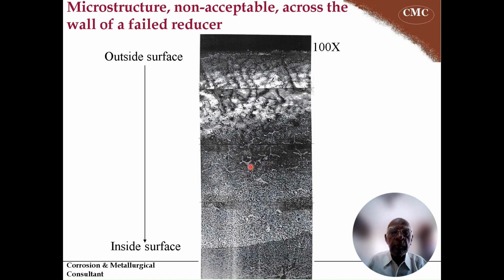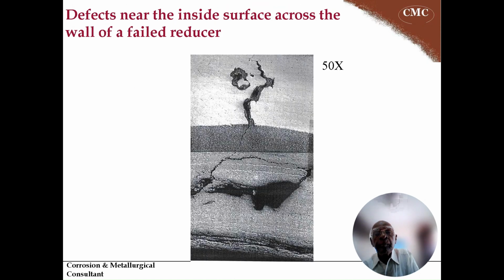The wall is only about 3 or 4 mm thickness, and due to the gradation in the microstructure, cracks develop. You can see the crack initiating on the inside, where hot gas is coming in, and then the cracks develop. Here you can see porosity, and cracks developing due to heating and cooling. Cracks develop on the inside surface and propagate towards the outside surface, resulting in leaking. And this is the typical failed reducer.